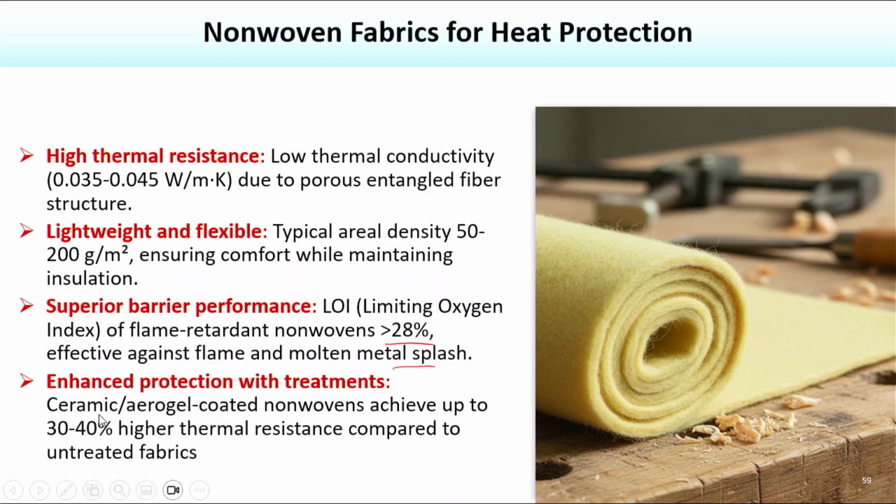It is enhanced protection with treatments. We can treat the non-woven to enhance the protection by ceramic or aerogel coating, which achieves 30 to 40% thermal resistance compared to untreated fabrics. We can increase the thermal protection performance of nonwoven fabric by treatment.